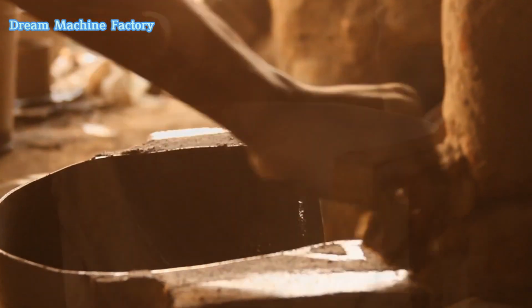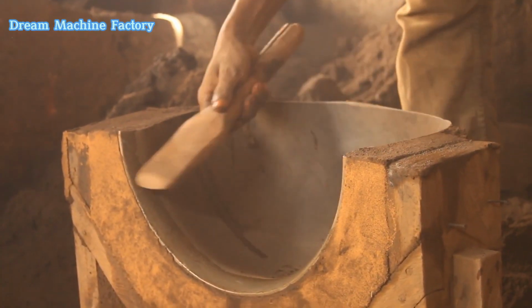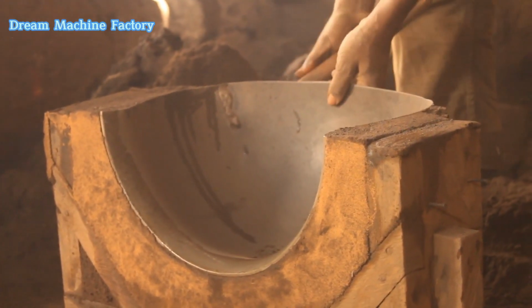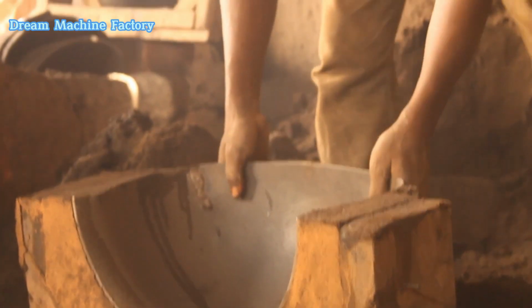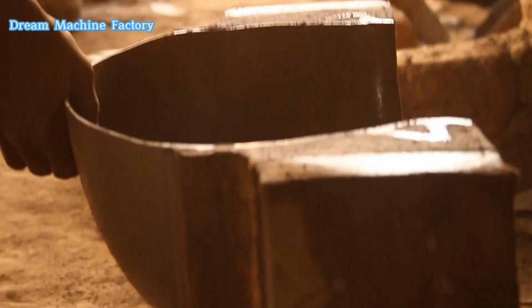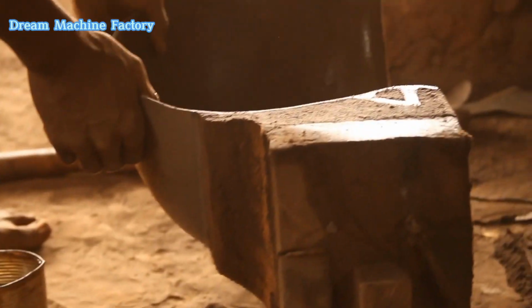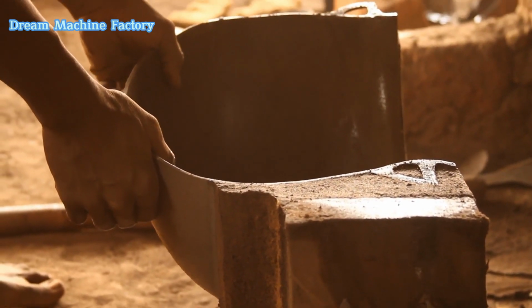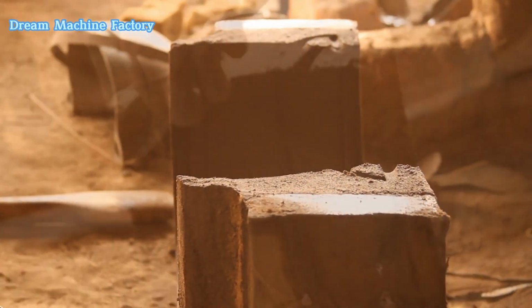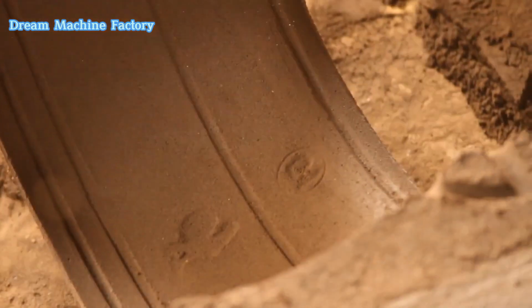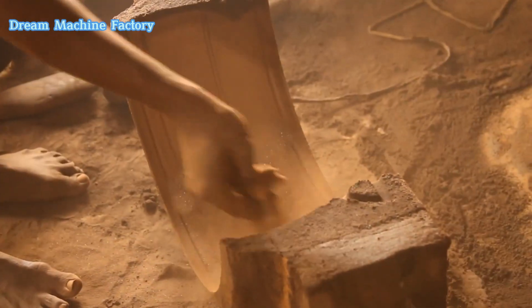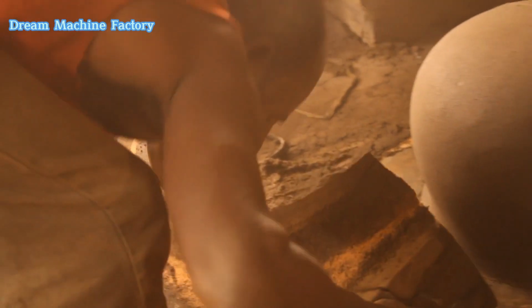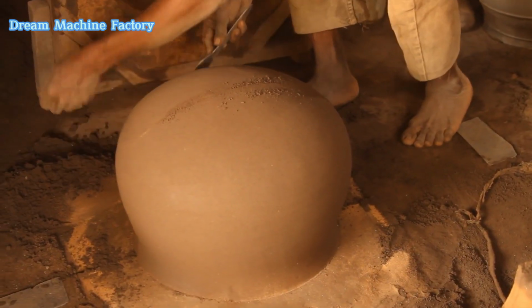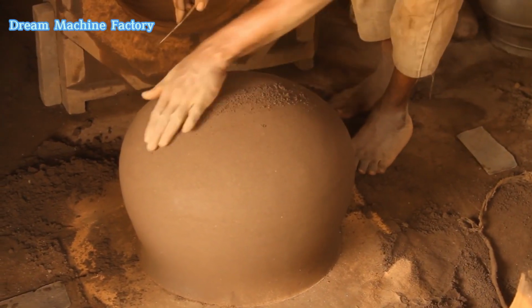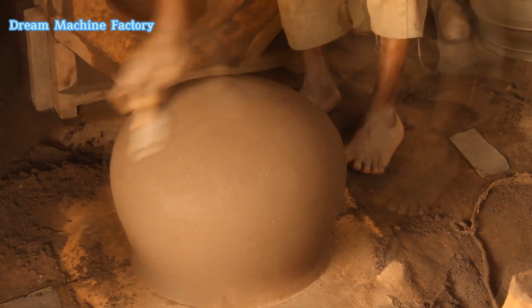Once the mold is packed, it is divided into two halves, the top half, cope, and the bottom half, drag, to allow for easy removal of the pattern. After the sand is firmly compacted, the artisans carefully remove the pattern from the mold, leaving a hollow cavity in the exact shape of the pot. If the sand is too loose or too dry, the mold may collapse, requiring the artisan to start over. Before the mold is ready for casting, the artisans create channels called sprues and vents to allow molten aluminum to flow in and air to escape. This ensures a smooth and even cast.